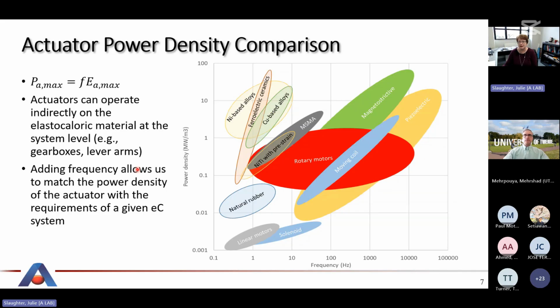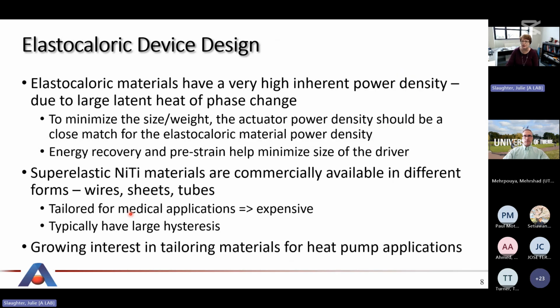So that's kind of where we're leaning to drive this, is how do you figure out how to use rotary motors? You don't want to use magnetostriction or piezoelectric. There's not a good way to translate the frequency into power density. So they've all got kind of this upward slope. So if you can operate at higher frequencies, they have higher power densities, but that doesn't really match what you can do with elastocalorics, because you're really limited to less than 10 hertz if you're acting in kind of this active regenerator mode. So that's just kind of a couple different ways to look at how you design the system and how you match actuators.